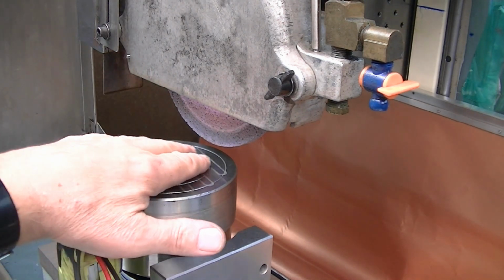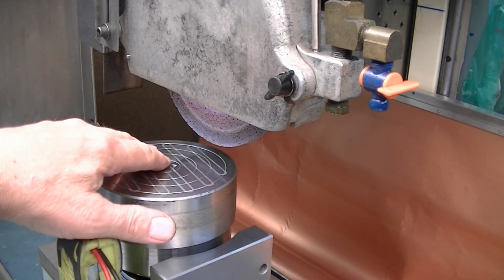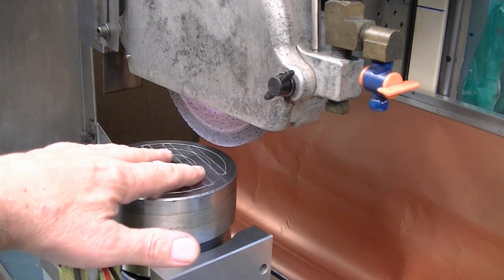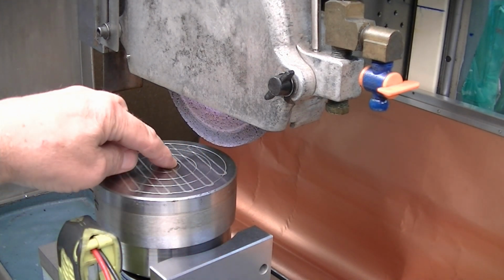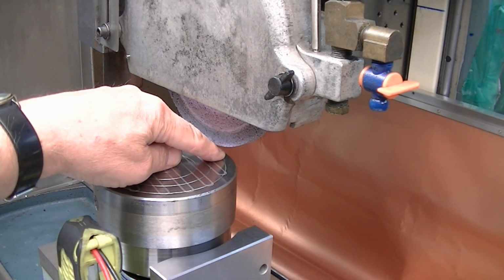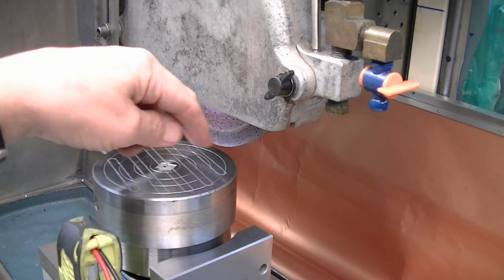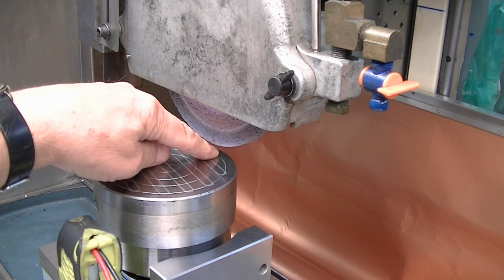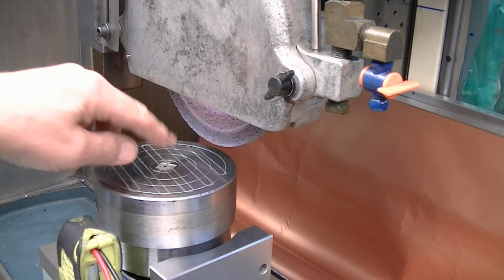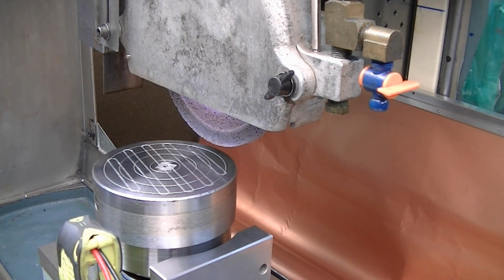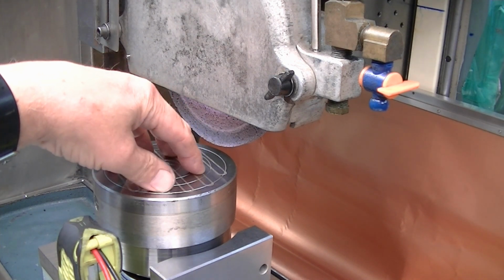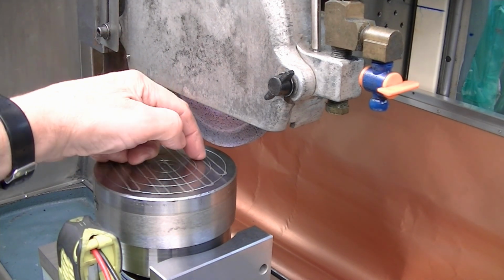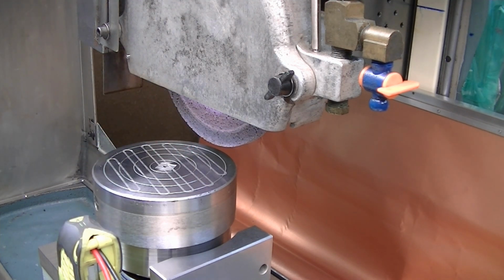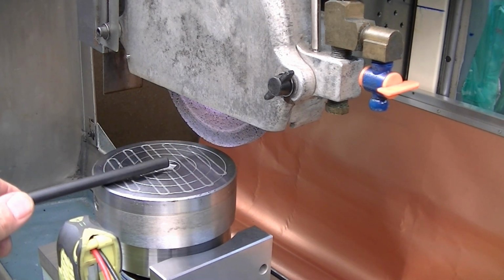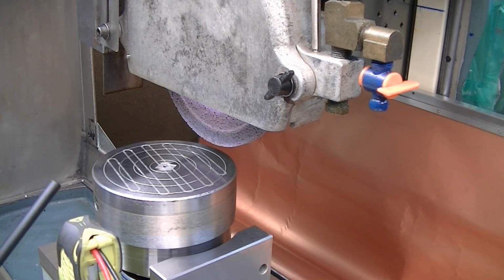On the same token, you have to be very careful when you're getting down to very small numbers about the wheel wear, the change in surface footage from here to here in the actual part surface footage as it's spinning. You've got very slow surface footage here, higher here, material removal rates higher here. All kinds of dynamics are involved, but if you're careful, you can get very, very true parts with this, and also, like we see in the examples in this video, of grinding round parts, grinding up to a shoulder, things like that.